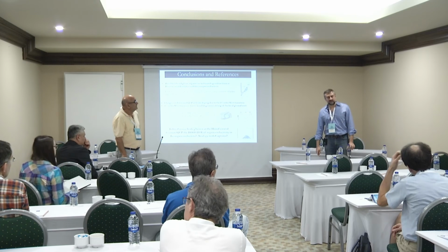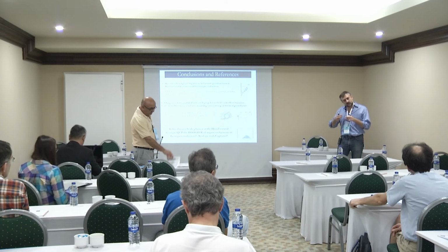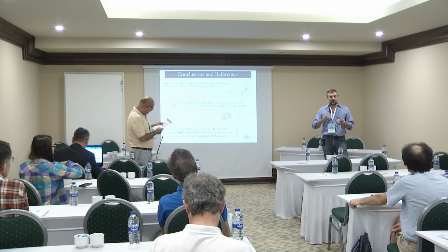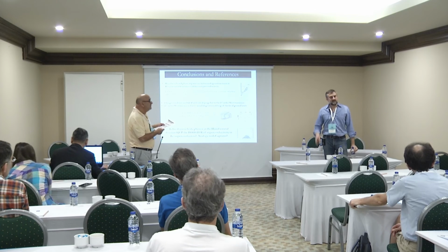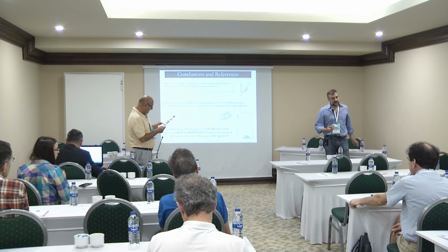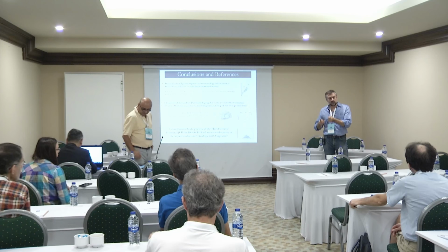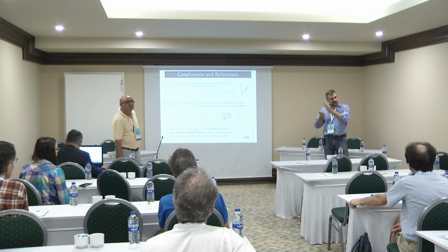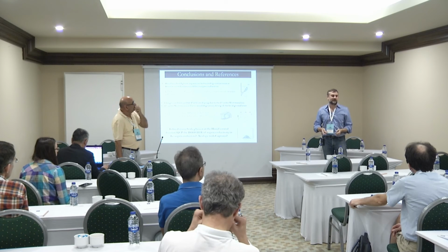The quantum critical point is pretty robust, and if you have crystal field splitting, it actually moves further away in doping. Now, we didn't study all the combinations of crystal field and bandwidth differences, but it's pretty robust. The only difference with differences in bandwidth between bands is that the zone of the strongly correlated metal is very prone to orbital selective correlations, so you can get a zone of orbital selective Mott insulator between the metal and the full Mott insulator. That's the main effect.